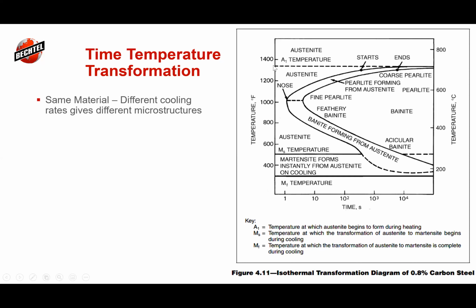Same way, if we have a heat affected zone that we're letting cool down nice and slowly, it's going to slow down and form this nice pearlite. As it cools down we expect it to form first a primary ferrite, and then a pearlitic matrix, and then it slows down nice and cool. I will say one more thing before I move on as we go through this.